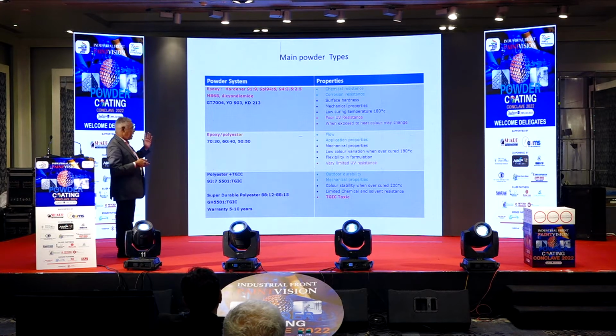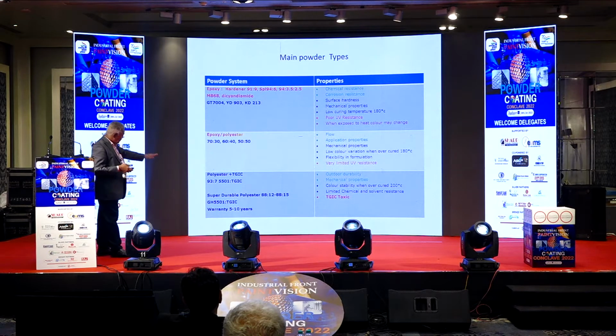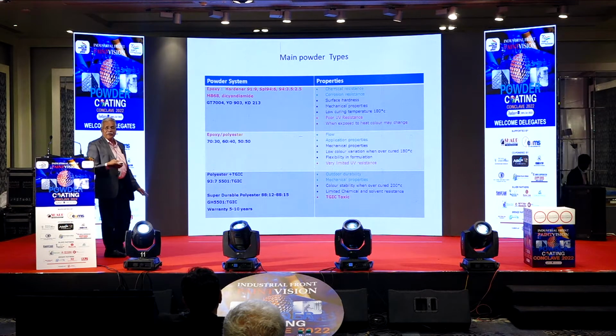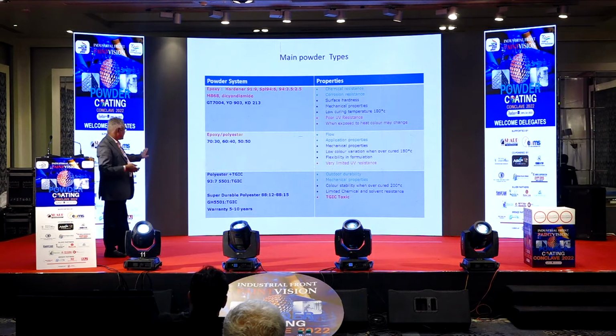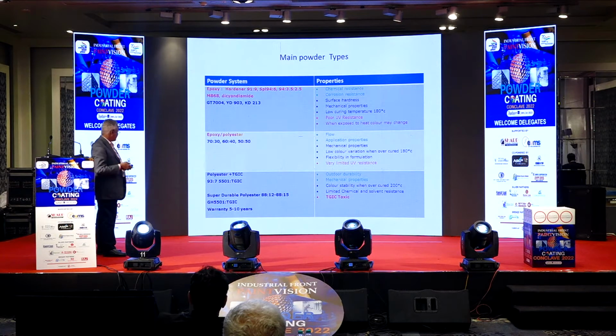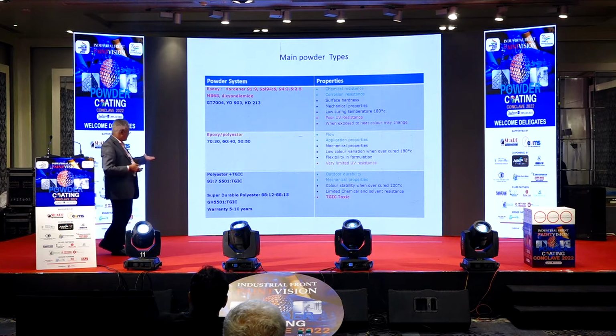Application property is very good. All other mechanical properties are moderate. Low color variation, meaning at 180 degree no change will be there. Flexibility in formulation, very limited UV resistance. That is already told. Then the lower one is epoxy-free, without epoxy. First is the polyester TGIC based combination. That is 93-7. You can generally use 93-7. You can slightly modify it also. We can do modifications for this and change.